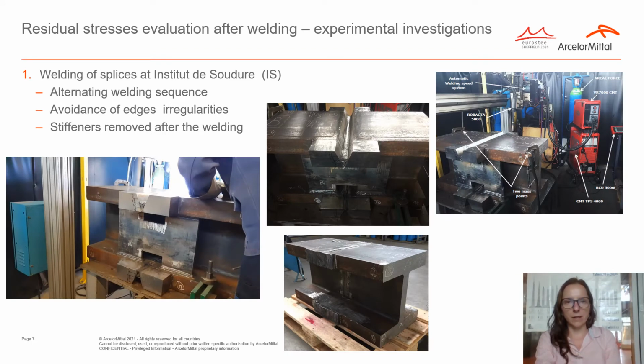As mentioned, the welding sequence was alternated between the upper and the lower flange in order to avoid additional constraints in the connection. The irregularities in the edges were avoided by welding run-on and run-off pieces at the extremities, allowing the weld to continue beyond the intended length. The stiffeners added before the welding were removed in the last step. The welding setup is presented in the top right picture.